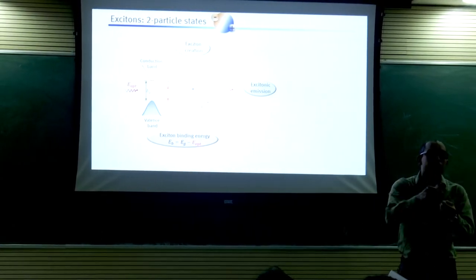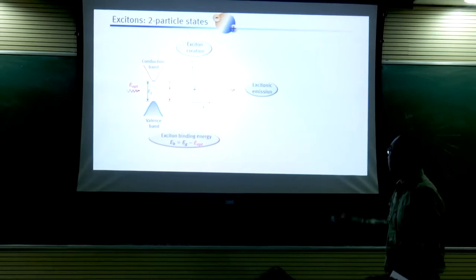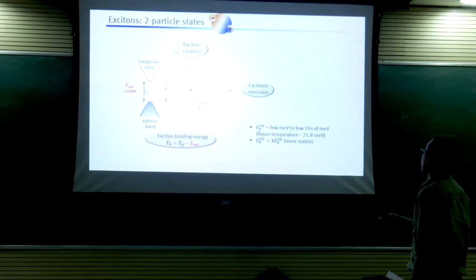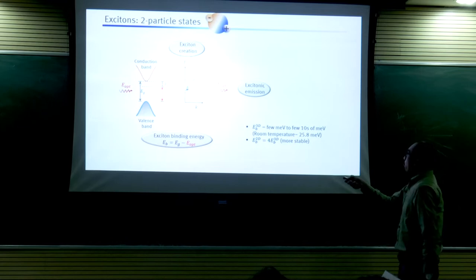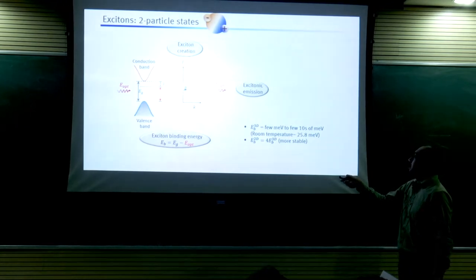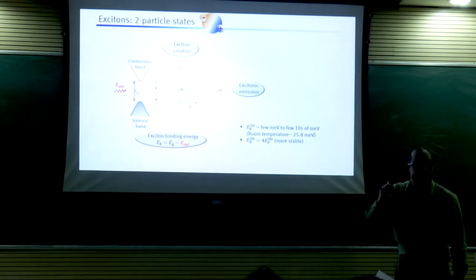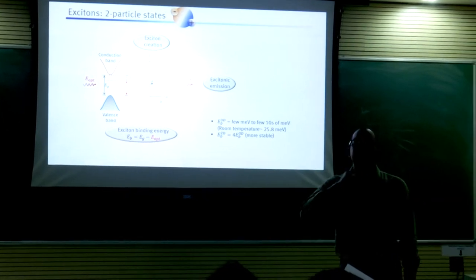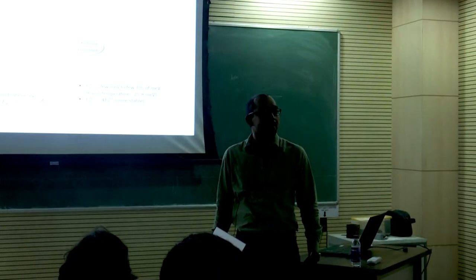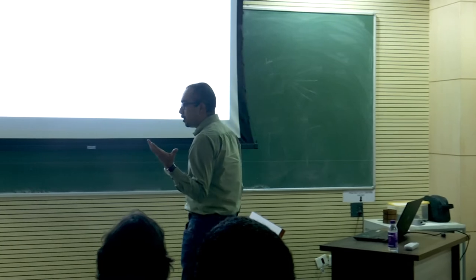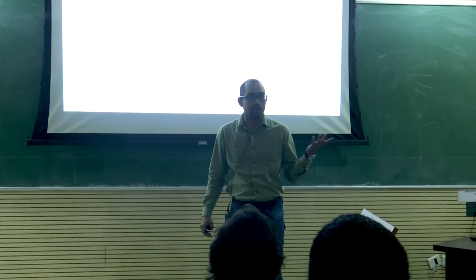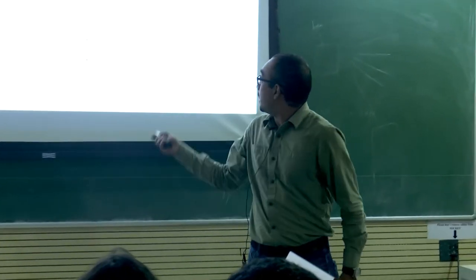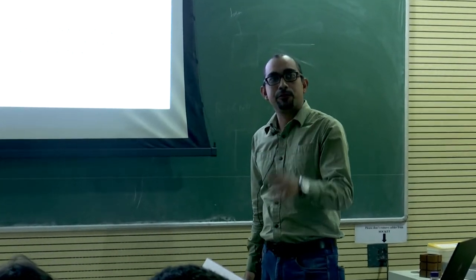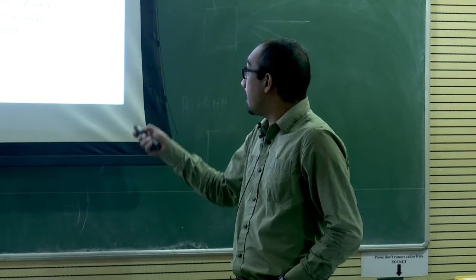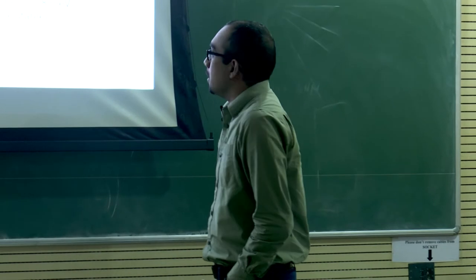And this exciton can emit light back: electron-hole pairs recombine, and they give rise to a photon again. So this is excitonic emission. Now the point to notice here is that the binding energy of this exciton in the semiconductor is much lesser than that of a hydrogen atom. In hydrogen atoms, the binding energy is of the order of 13.6 electron volts. So it's in electron volts, but here it's 1000 times lesser. It's a few milli electron volts to a few tens of milli electron volts.